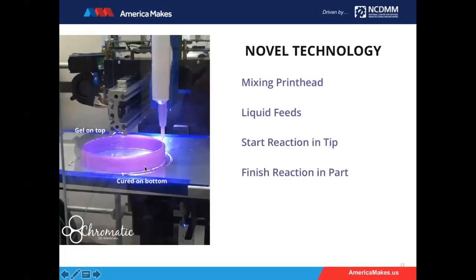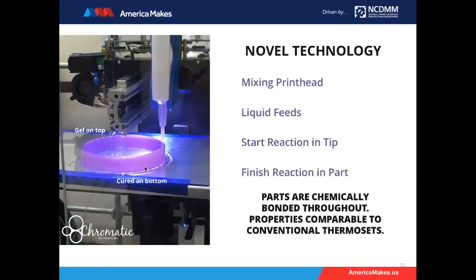And this brings a lot of very important attributes to 3D printing. The first most important element is that the parts are chemically bonded throughout. It's like we're printing with a Gorilla Glue, because as we're laying down each layer, it is chemically bonding to the layer below. Furthermore, because the material is not completely reacted when it comes out, it's able to react with the material side by side, and it can also flow slightly in order to fill all of the voids that could be formed in a standard FDM process. So the result is that we're able to make printed parts that have properties that are comparable to those conventional thermosets.